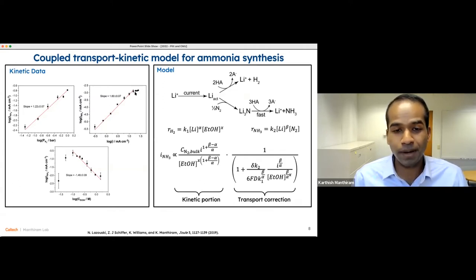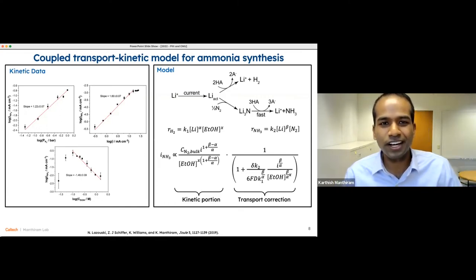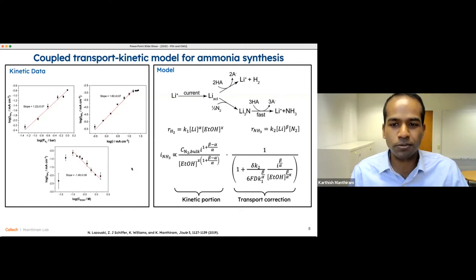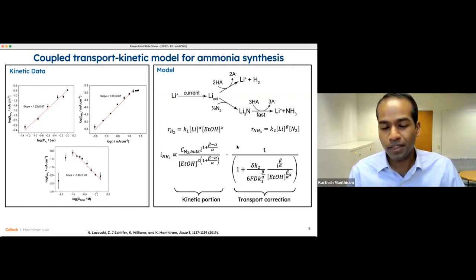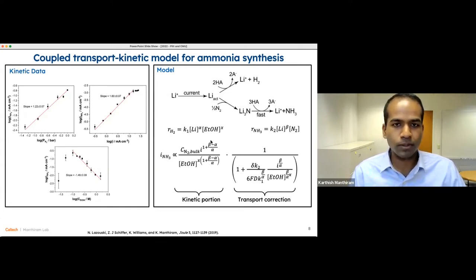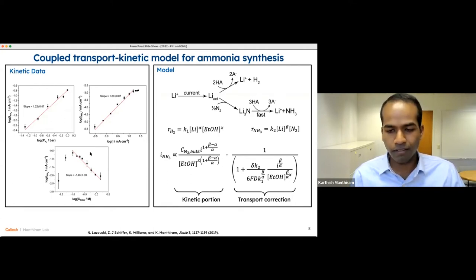We can also tell just by adding in a stir bar and stirring faster that the rate goes up. So that gives us a very clear confirmation that this is in fact a transport limitation. So that means that this model needs a second part. A kinetic portion is insufficient. So we need to add in a transport correction. And you'll see here variables like delta, the boundary layer thickness, D, the diffusivity. So we're accounting for transport characteristics. And together, these two parts are able to quantitatively predict partial currents for ammonia across a wide range of operating conditions.